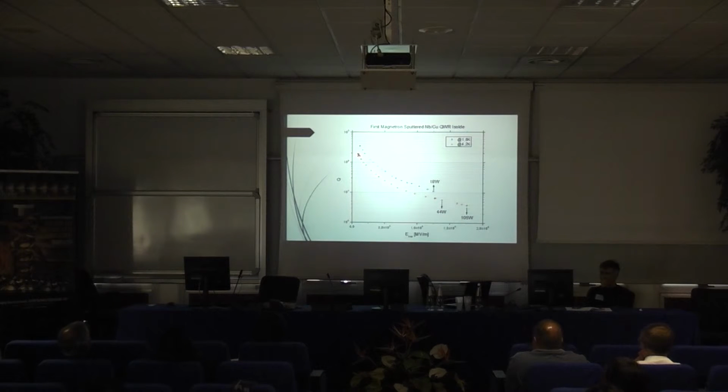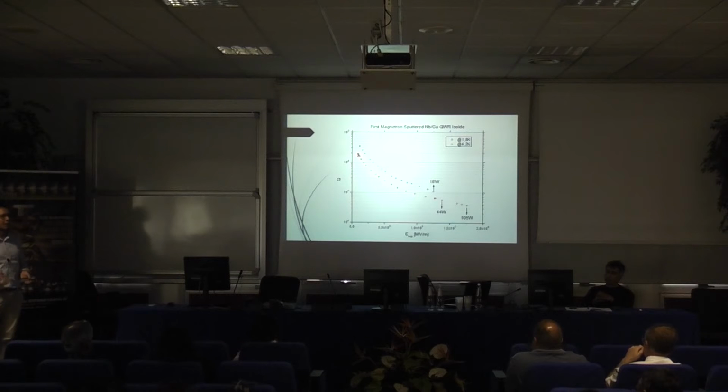That's the plot of the Q against the accelerating field. The Q is not the best, it's below the CERN specifications, but the Q0 here is 2×10^8. I think this is not so bad, so we are really motivated and we think that we can improve these results, maybe trying to decrease the distance between the cathode and the top of the cavity, as Alban has said. I think it was the same problem that CERN had before.